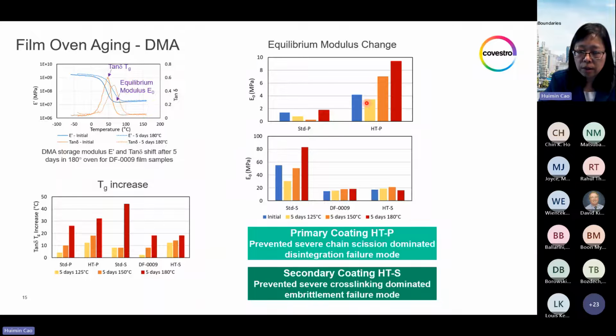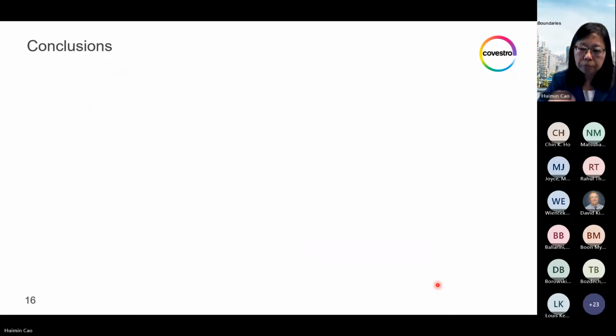And then for the rest of the aging time, it slightly goes up, but still way lower than the standard type of modulus. The high temperature HTS shows a remarkably stable equilibrium modulus, similar to DF-0009, very stable and much better than the stability of standard secondary coating. The Tg shift is also much lower than a standard secondary coating, which will result in a much better retention of material toughness, avoiding the failure mode of embrittlement, secondary embrittlement at high temperature.